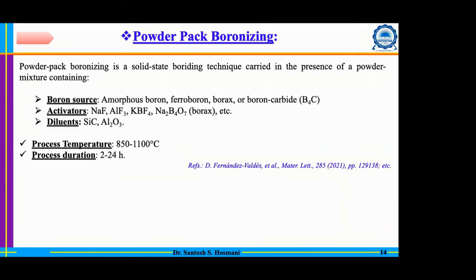B4C, boron carbide, is also widely used, and the activator is mostly KBF4. So basically a halide type of compound is generally used for the activators. And the role of a diluent, in principle, is just to provide an inert atmosphere so that whatever environment is generated will be pretty uniform surrounding the specimen surface. That is the role played by the diluent. And mostly people use SiC as a diluent. This SiC is considered to be inert at the boronizing temperature.